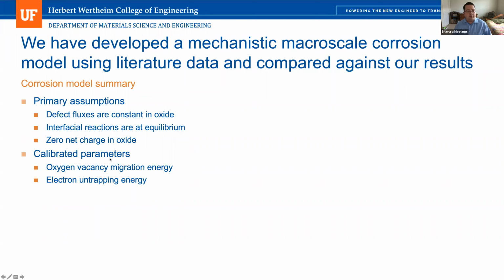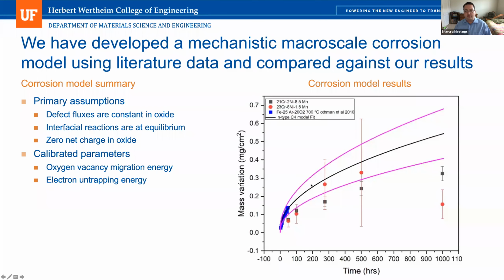And then we have calibrated parameters that we set by comparing to experiments. And then we have the oxygen vacancy migration energy. We may eventually replace that with DFT results. And then we're also fitting the electron untrapping energy. So we've done initial fitting of our model by comparing to experimental data from the literature for a stainless steel alloy without manganese. And then we compare the corrosion rate, and we get reasonable comparison within 25% error, which is the pink lines, with the 23-6N results that have the small amount of manganese. But we are not getting good comparison with the 21.2N, which has a lot more manganese. So this again shows us the importance of manganese.